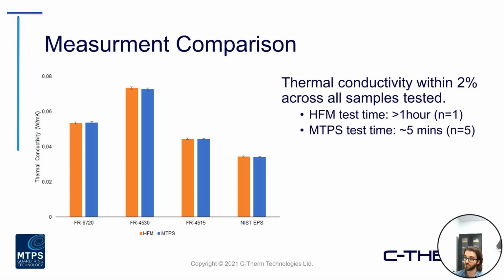The biggest differentiator between these was the fact that your heat flow meter test times were generally on the order of an hour or more, whereas with your MTPS, we're able to get 5 back-to-back measurements in about 5 minutes. So really just highlighting those speed differences between the methodologies.